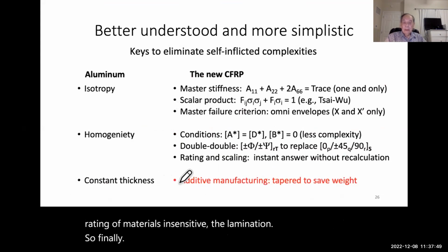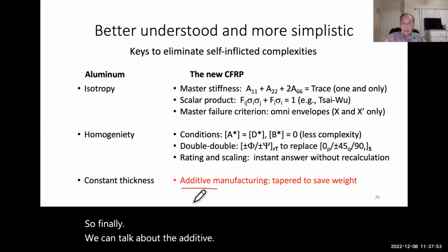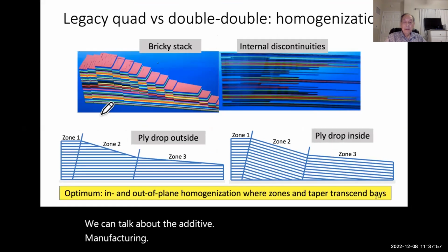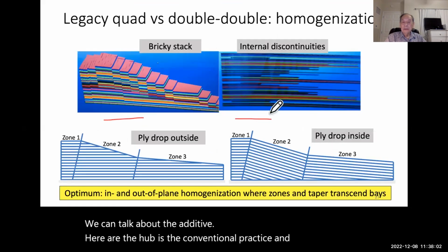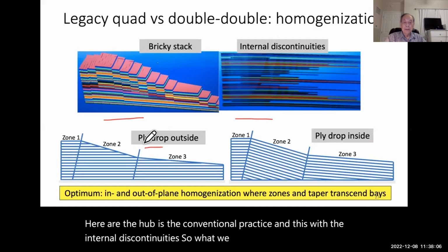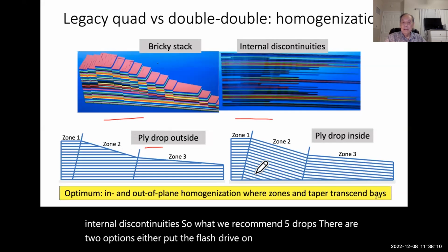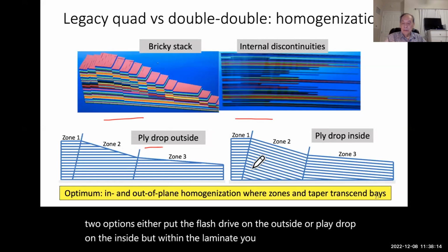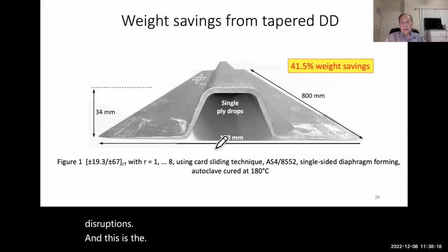So finally, we can talk about additive manufacturing. Here on the top is the conventional practice, with the internal discontinuities. So what we recommend for ply drop, there are two options: either put the ply drop on the outside or put the ply drop on the inside. But within the laminate, you can see there are no disruptions. And this is a stiffener made by DFVLR. It has a taper, and the taper is the thinnest at the edge and then the highest in here. And the savings is 41%. And it is stronger because it does not have a peel stress, as you have a constant thickness.